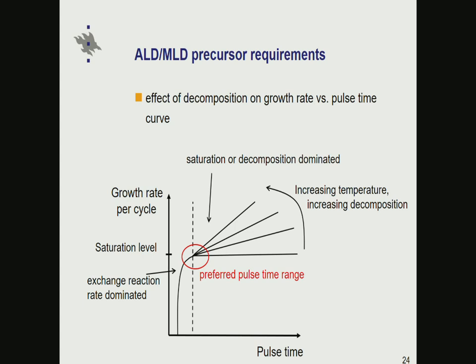So how we observe decomposition in these growth rate per cycle curves is something like shown here. This is the pulse time for, in most cases, the metal precursor. What we observe in the beginning is that there is a very fast increase of the growth rate towards the saturation level. And now if we are working under true ALD conditions, once reaching the saturation level, nothing more is being deposited. On the other hand, if we are exceeding the decomposition limit, we start to see these kind of linear curves here. And of course, the higher the temperature, the more decomposition is taking place, and the higher the slopes of these will be.